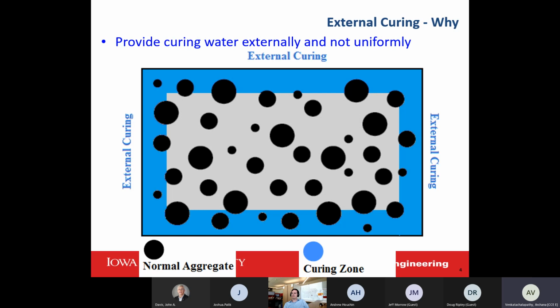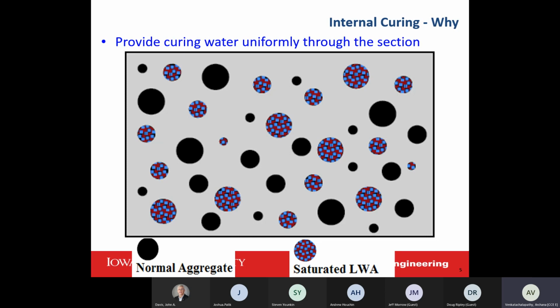And curing is a very important part of the concrete life in the first 28 days, because hydration means the chemical things are happening in the concrete to make the concrete harder and stronger. But internal curing means we try to use some materials, either SAP or lightweight fine aggregate, that we used here, that can hold more water, for example 10 times more than the regular aggregate. And it does not add water to the concrete at the time of mixing, because if you add just, I don't know, 1 gallon of water to a whole truck, you screw the concrete.